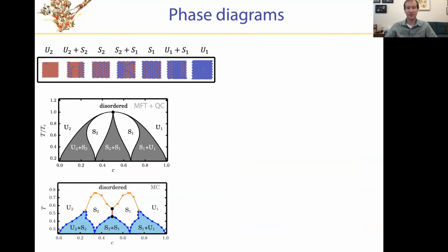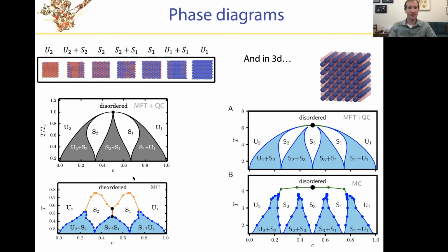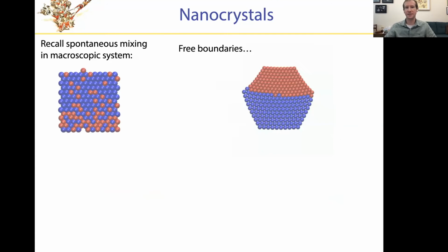Right, we can map out these phase diagrams in quite a bit of detail using both theory and simulation. And that's something we've done in 2 dimensions. I showed you results in 2 dimensions because they're easy to look at, but very similar behavior in 3 dimensions, where again, these modulated phases emerge. So we have this interesting conundrum that elastic biases favor pure materials that are unmixed. But once I force them to have an intermediate composition, what they do is not to separate, but instead to mix in this highly ordered fashion. So what are the consequences then for this process of cation exchange?